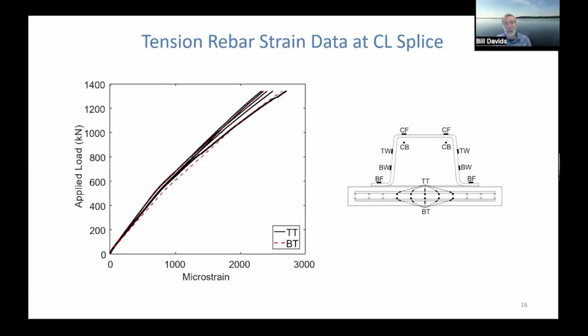To reinforce that, this is a plot of applied load versus strain in the tension reinforcing. So that's the reinforcing in the deck on the bottom. And we instrumented a lot of bars there. There were 5 bars instrumented in the top layer, 5 in the bottom layer. And you can see the plot here, very consistent strain readings. And the peak ones are up around 2,700 microstrains. One takeaway from this is the steel did not yield.